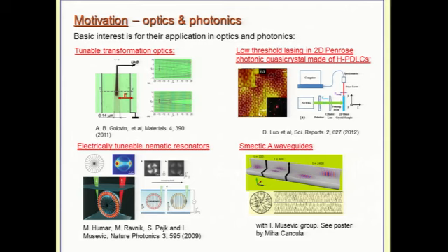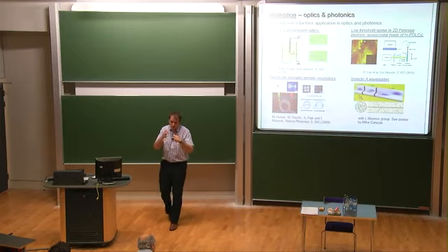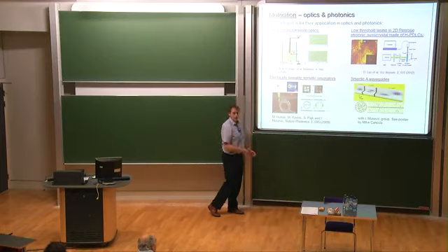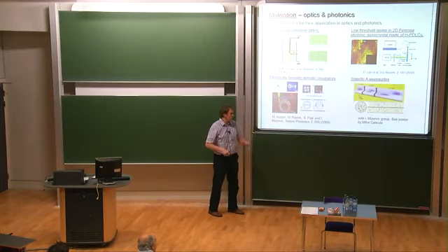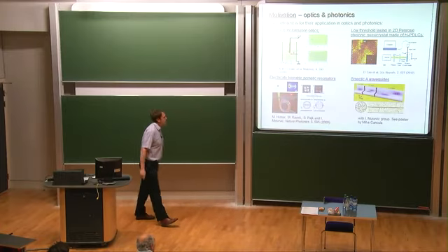What you do is shine a laser into the droplet, and it turns out that this light starts to circulate around the droplet. To be more precise, whispering gallery modes emerge in such droplets. By changing the profile of the nematic droplet, for example with external fields, you can change how this light circulates in the droplet.